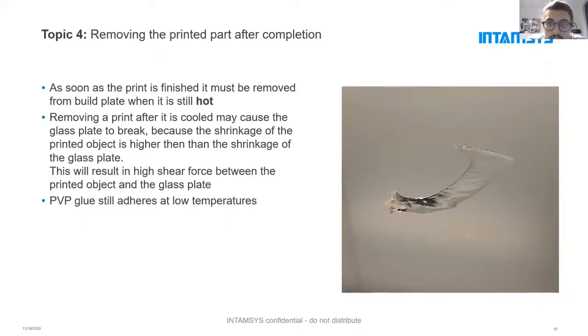to avoid any high force to the surface of the glass plate, as the glass plate is very hard and slightly brittle. This is especially related to the Dimafix PVP glue that we do recommend, as that glue still has a high adhesion at low temperatures. Some other glues in the market, like Magigoo HD, which gives you a little bit less adhesion, also lose their adhesion at lower temperatures. So there is less risk, but there's still a risk that your part has too high adhesion to the build plate, and this results in a broken glass plate.